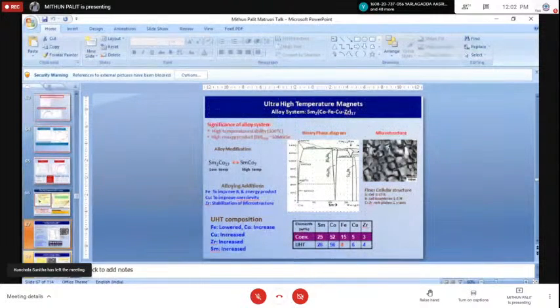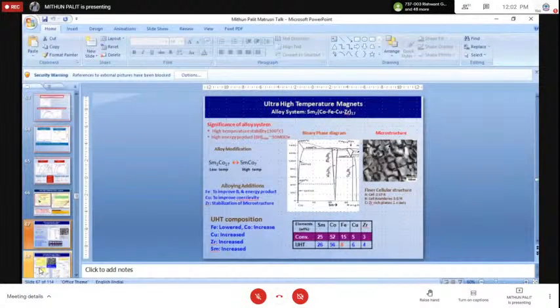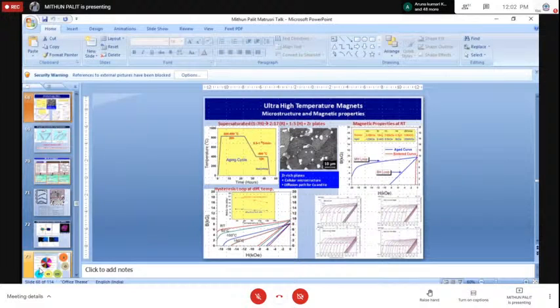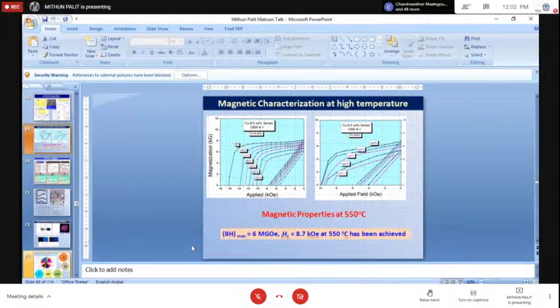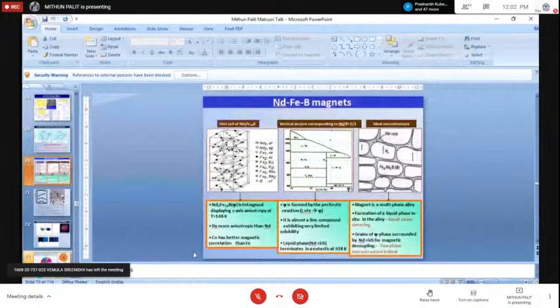As I told you, this is a 5-element system, so we have to strike a balance between iron, copper and zirconium along with samarium, and by doing that you can develop a very high temperature grade of magnet. We can see in this plot that the magnetic properties are measured at different temperatures, and in fact by tuning this composition we have developed an ultra high temperature magnet which can work at temperatures up to 550 degrees centigrade.